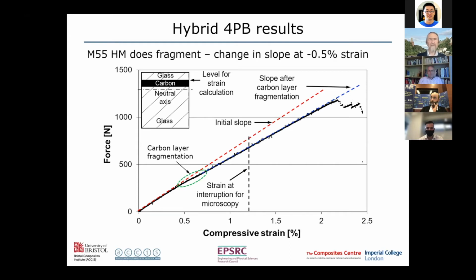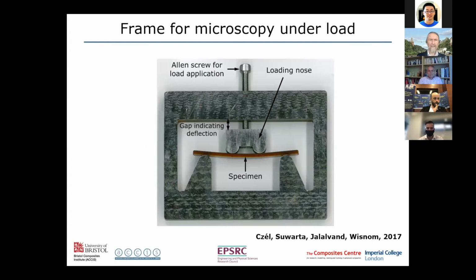So to understand what was happening there, we did some interrupted tests where we took them to 1.2% strain, so well beyond this knee point, to look at what the damage was in the specimens. And we had a little jig here, so we could actually load it and unload it under the microscope to look at the development of damage.